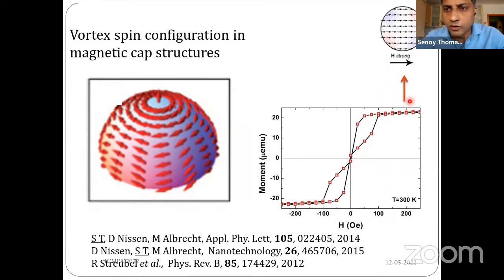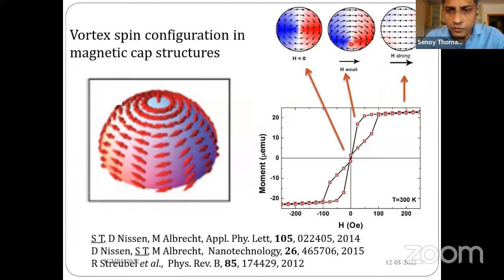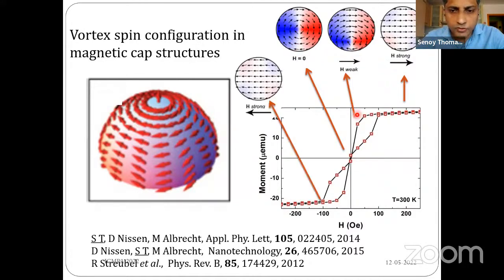At very strong positive field, it is possible to align the magnetic moments of the cap structures along the field direction. Once you decrease the field and reach the nucleation field, you could nucleate the magnetic vortex. Once you decrease the field to zero, the core of the magnetic vortex shifts to the center of the cap structures. Once you increase the field in the opposite direction, the magnetic vortex core will get annihilated from the system, and you will get a uniform spin configuration, which is saturated in the opposite field direction.